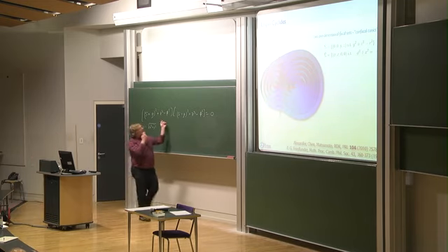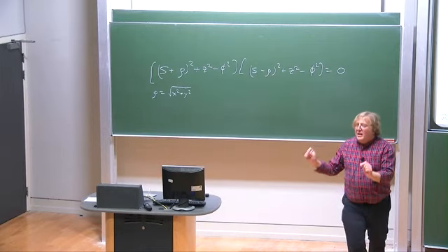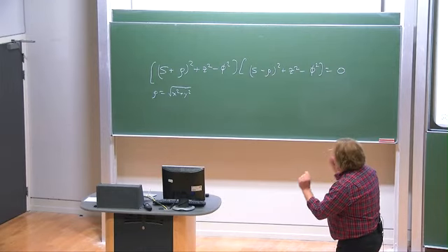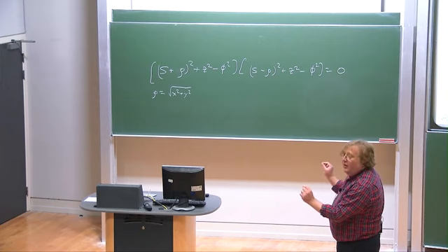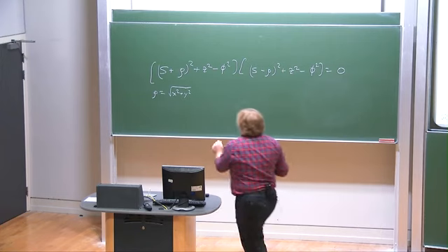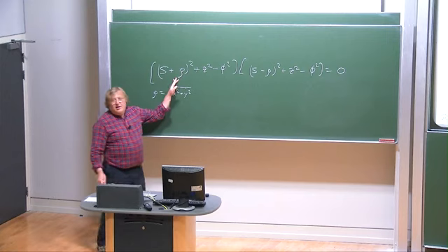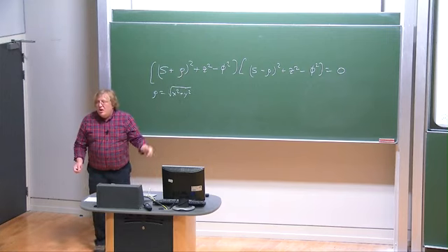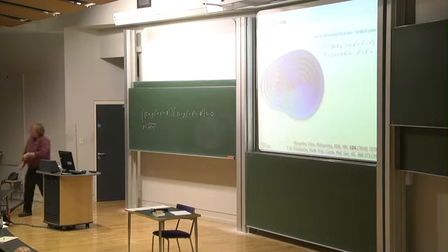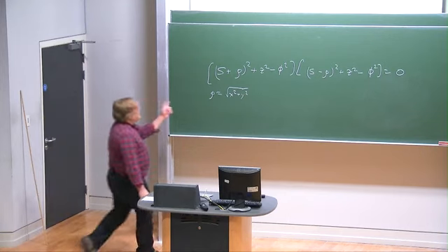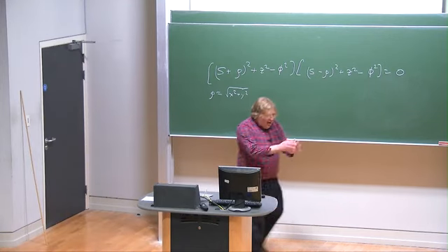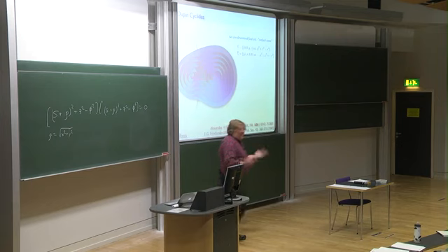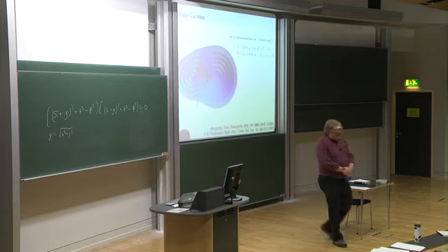Because look, I've written this thing now. I've written the Cyclide of Dupin as the product of 2 cones. Cones in funny coordinate system. This is sort of radial coordinates, but so what? They're cones. So I know that the Cyclide of Dupin, those concentric Cycloids, are equally spaced. No calculus, just algebra. Because what I've shown you is it's the product of 2 cones. And since a cone gives me equal spacing, the product of 2 cones will also give me equal spacing.